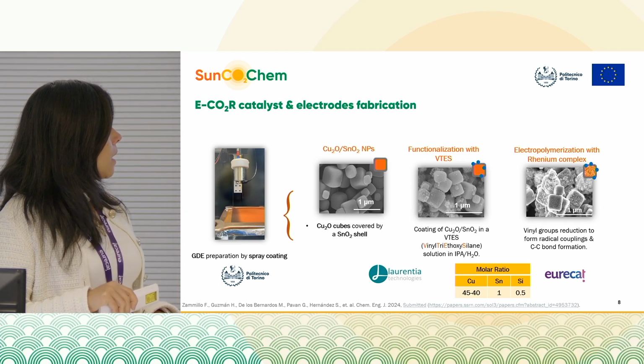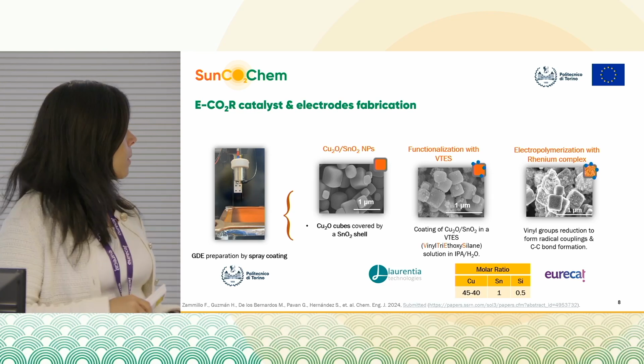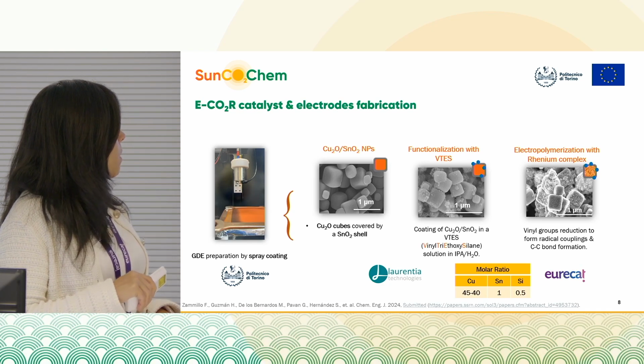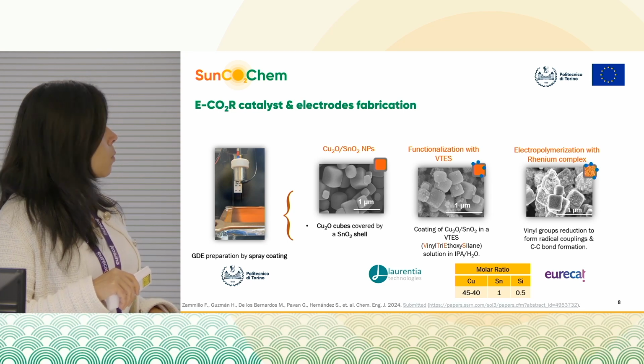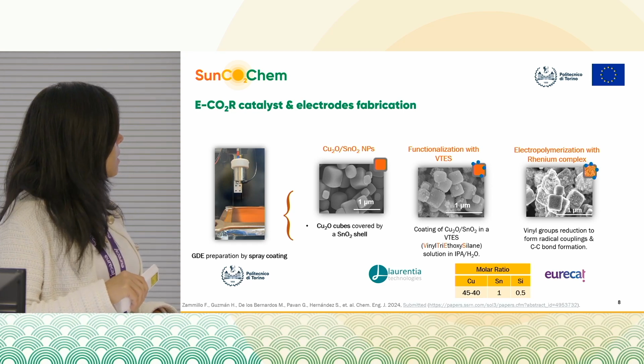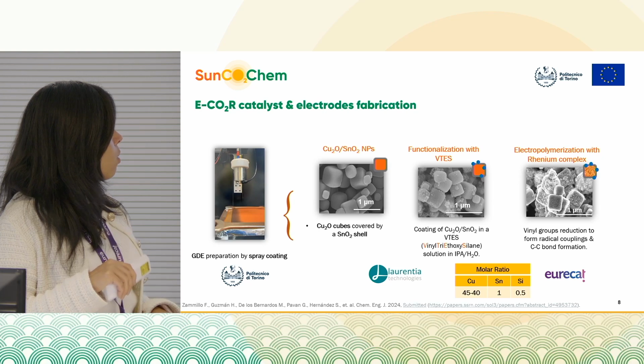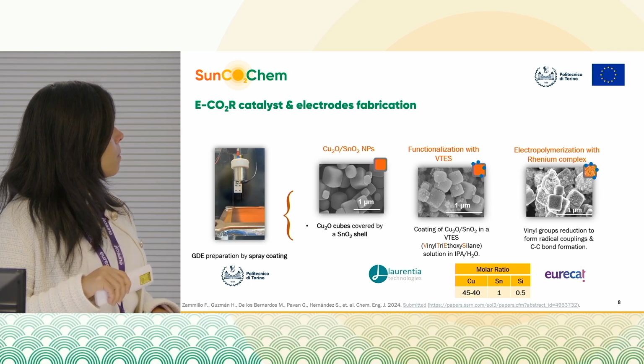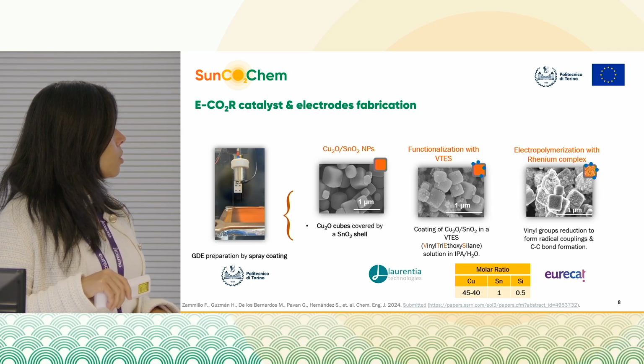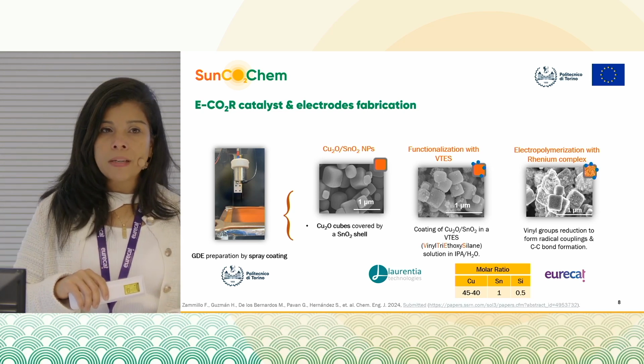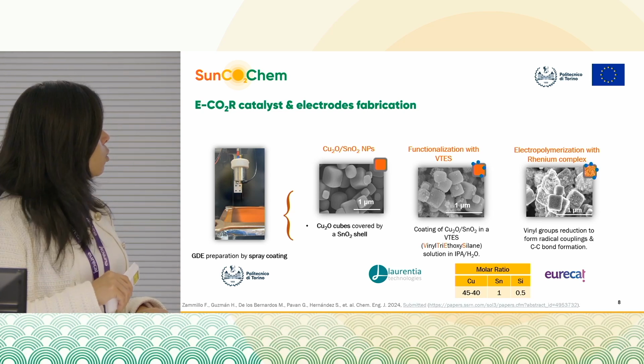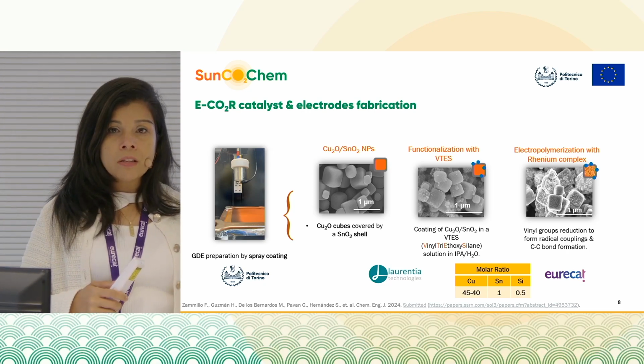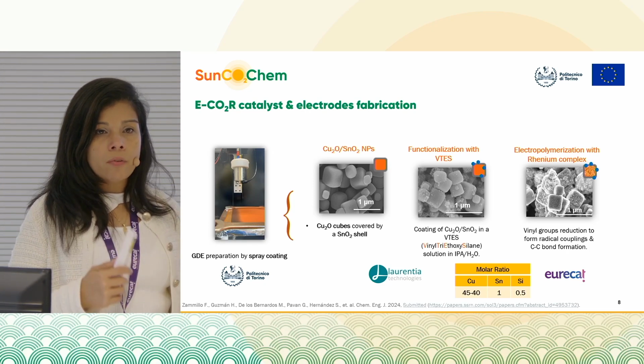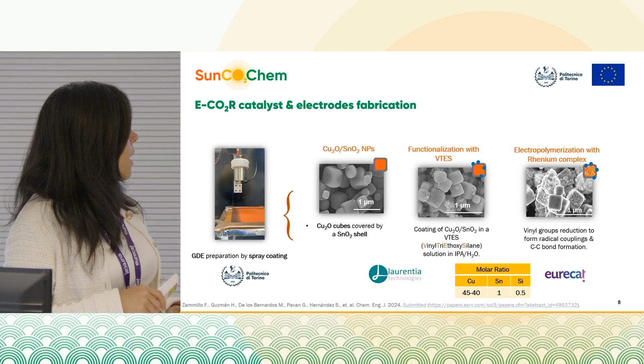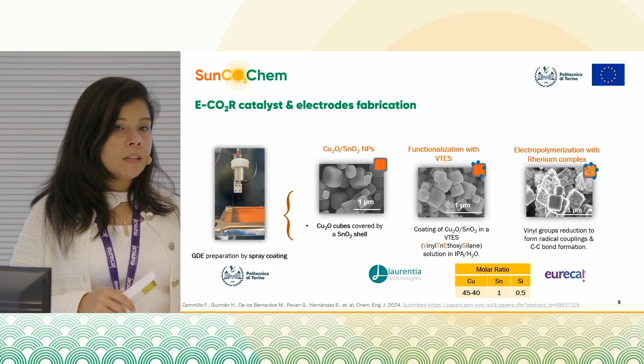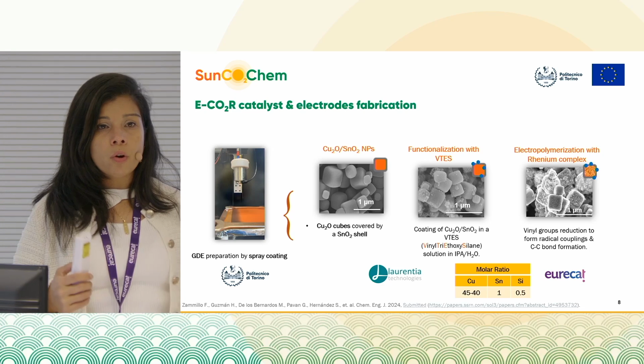Here you can see the details of the catalyst that was developed in collaboration with other partners. So we prepared nanocubes of copper oxide, with copper plus oxidation state that was stabilized by a shell of tin oxide, and then with some functionalization, we were able to anchor some rhenium complexes on the surface of the catalyst. And through this technique, that was scaled up by Laurencia up to close to kilograms, we were able to develop a very selective catalyst not containing noble metals for syngas production.